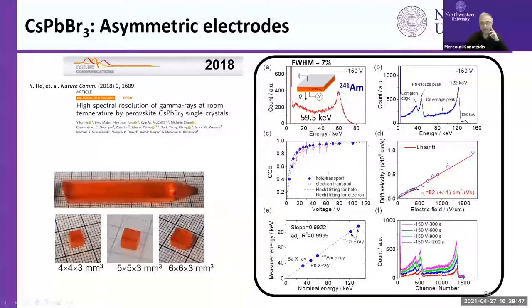And this was reproducible. And this is basically the charge collection efficiency as a function of voltage. We have very nice results, reaching almost 100% efficiency after about 60 volts. We measured the drift velocity and calculated the mobility, which is about 50 square centimeters per volt second.